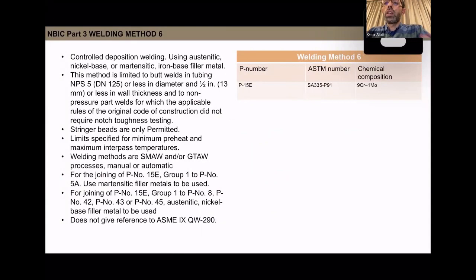Number 6 is using austenitic filler for similar weld for P91 material, the 9 chrome 1 moly, using controlled deposition. This is limited to butt weld in tubing, 5-inch or less diameter. Stringer bead only is permitted. Limits specified for minimum preheat and maximum interpass value are specified. Welding method is SMAW or GTAW process, manual or automatic.